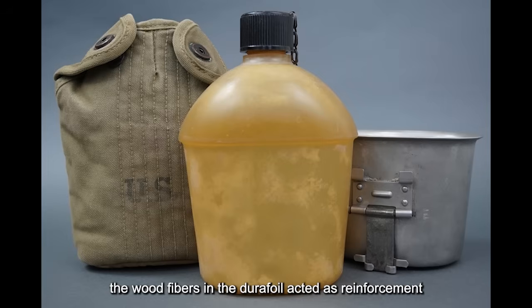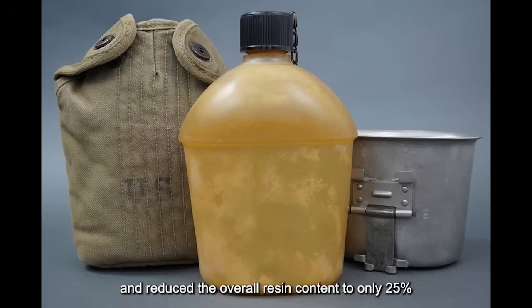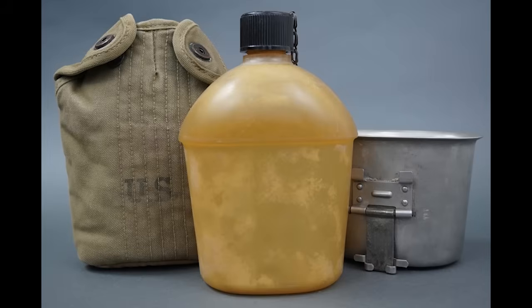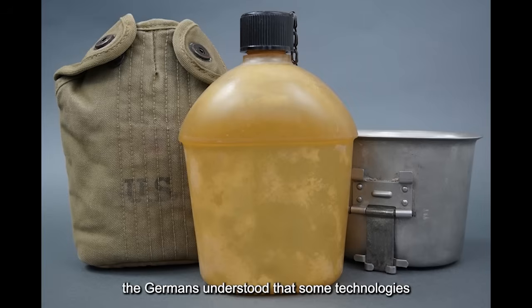The wood fibers in the Durofol acted as reinforcement and reduced the overall resin content to only 25%. The bulk of the composite was wood, not plastic. This created a material that was strong, stable, and cheap to manufacture. But the key insight was architectural. The Germans understood that some technologies should be proven and reliable, not experimental. The aluminum water reservoir was proven technology going back decades. The phenolic composite shell was the innovation.